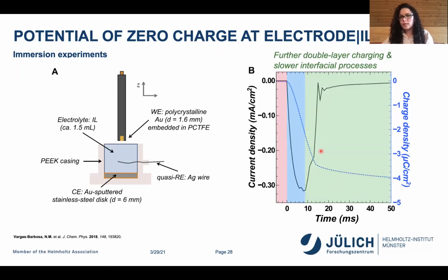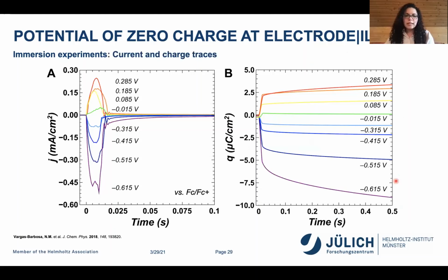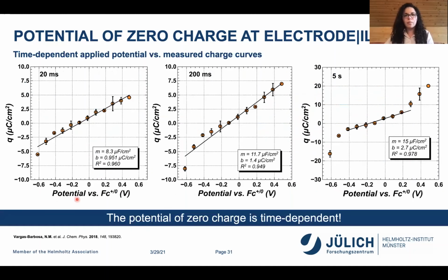And so we can take the integral of this and we obtain the charge. And so we did this at different potentials, and we obtained the different charges. And then we did a time-dependent analysis. So at different time points, we looked at what was the current that had flowed in the system at a specific time. And so we were able to generate these potential-charge curves, which have the potential here on the x-axis and the charge on the y-axis. And what we observe is that as time proceeds, this curve changes significantly. And when you do the fitting, it seems that the potential of zero charge is a time-dependent parameter in these systems.